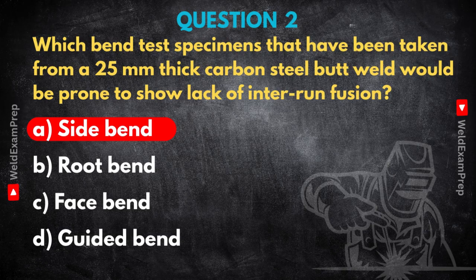Okay. But bend tests, especially side bends for thick materials, play a different vital role. They're destructive tests used primarily for qualifying welders and welding procedures. Proving capability. Exactly. You're proving that a specific welder, using a specific procedure, can produce a weld that's internally sound and has the right mechanical properties. The side bend test, by physically pulling those layers apart, gives you that tangible proof for qualification purposes.